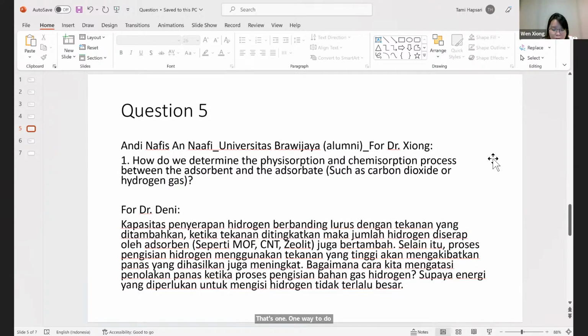The other way is using temperature programmed desorption. You flow CO2 or hydrogen, for example in the AutoChem flow system, to the sample, and the sample will both physisorb and chemisorb the gas on the surface. You dose for a certain time to saturate the surface, like 3 hours or 6 hours, whatever you need. Then you flow an inert gas, like helium or argon, to the sample and run the temperature program from wherever you start, like 0 degrees C or even 25 degrees C. In this way, you can see the gas desorption from the surface as a function of time.